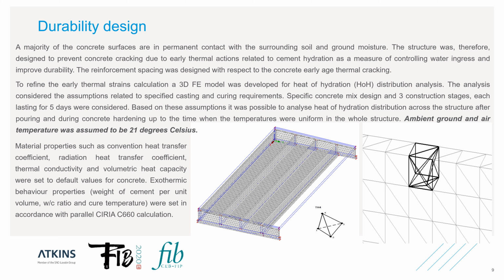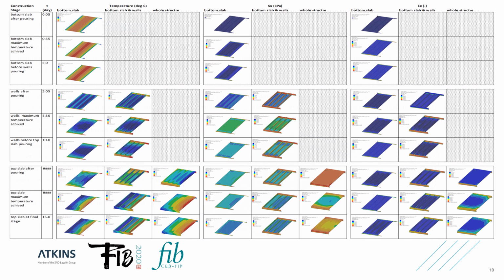Exothermic behavior properties, weight of cement per unit volume, water to cement ratio, and cure temperature were set in accordance with the parallel CIRIA C660 calculation. The figure shows the volume FE model developed for heat of hydration analysis. Each concrete member was modeled as a 3D volume and meshed with tetrahedral elements.